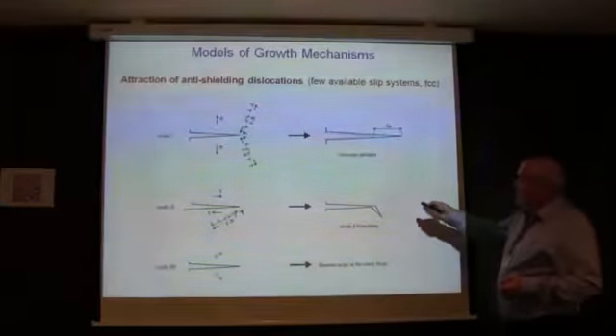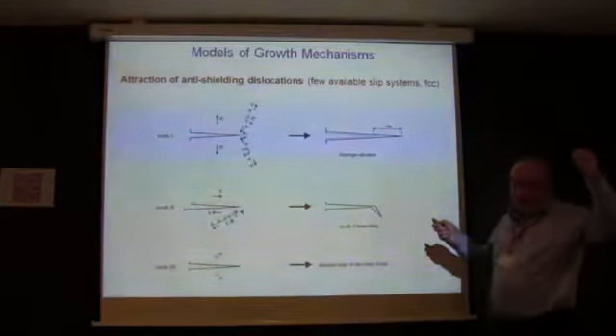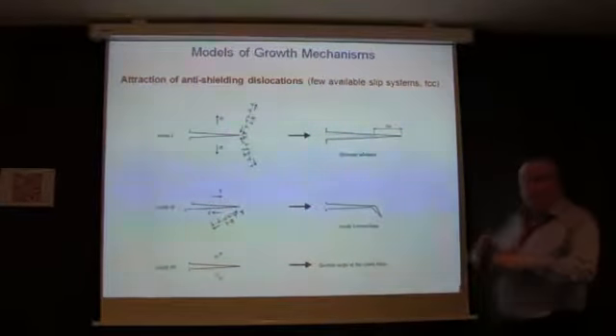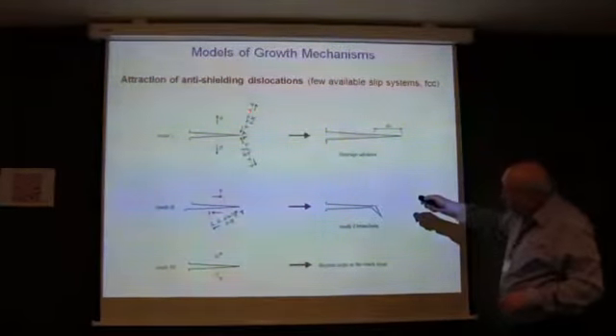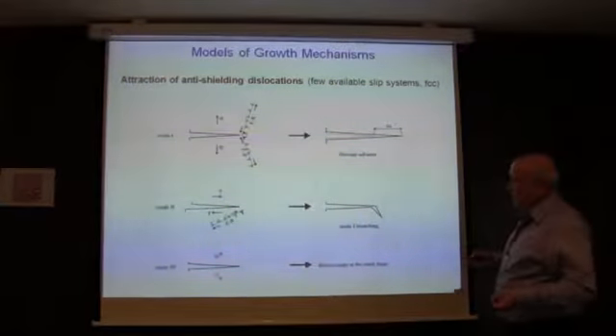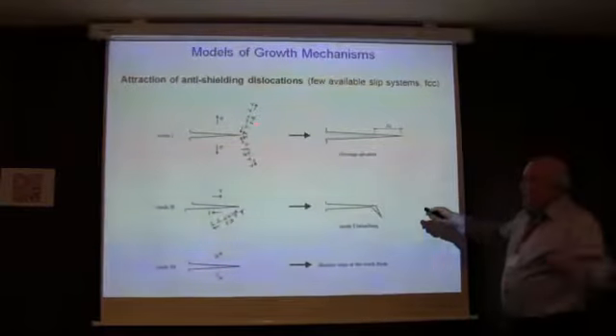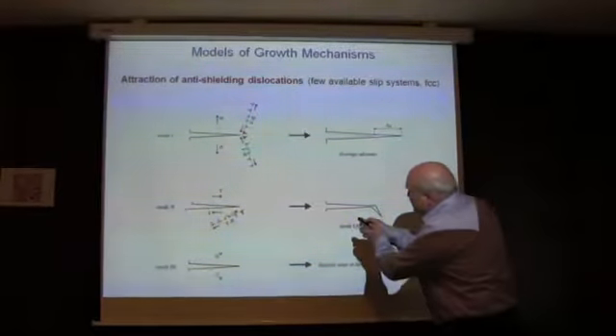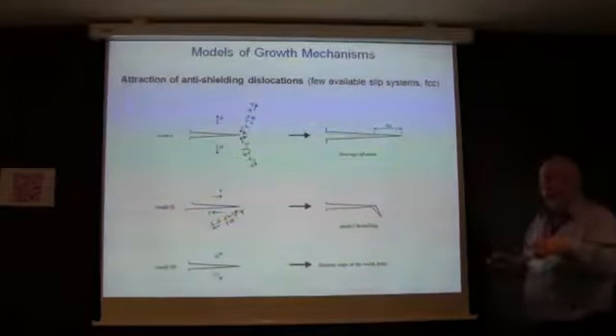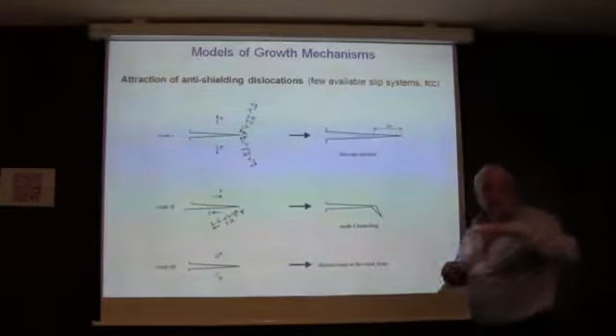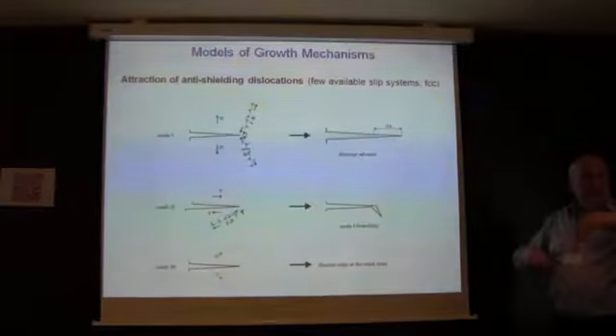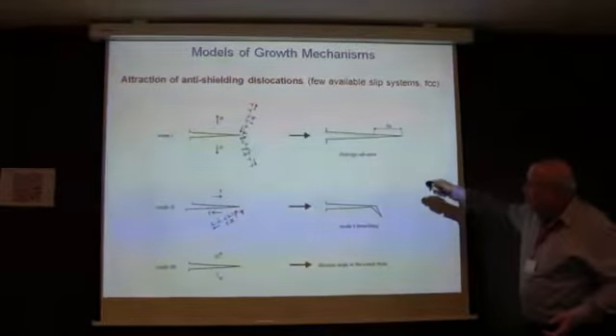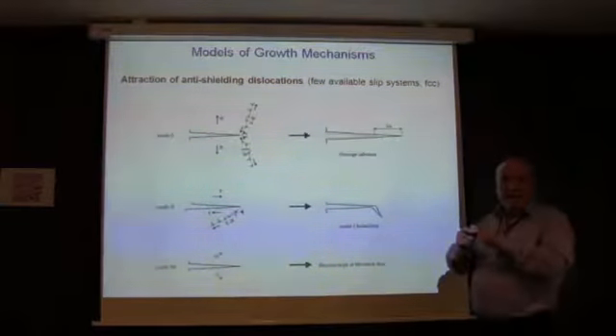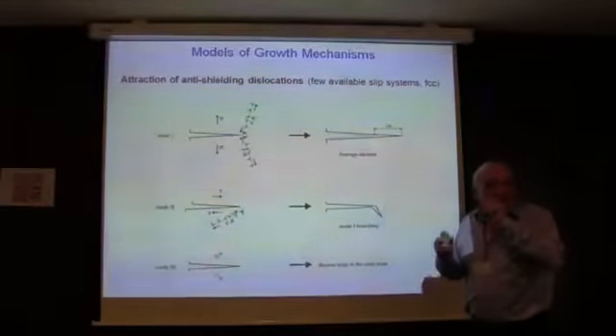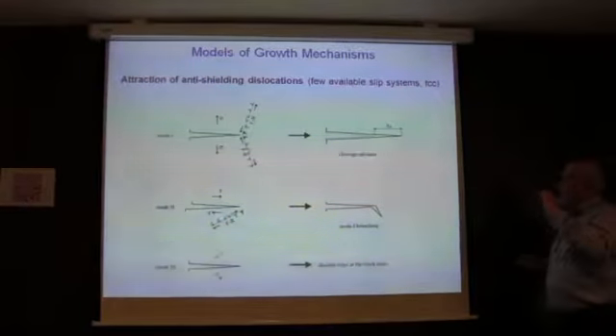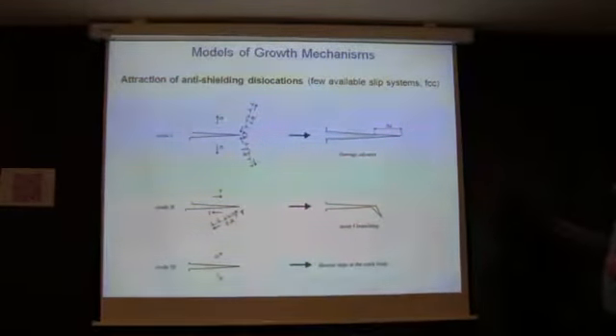So this is actually something. You have external sources of dislocations. And in that case, if you would like to open the crack, you have to just absorb the anti-shielding dislocations. And so what can happen? If some anti-shielding dislocations like this come from the external sources to the crack tip, they apply an internal tensile stress field on the crack, which can be superimposed with the axial stress, and the crack can propagate by decohesion. Say a nano cleavage, like this.